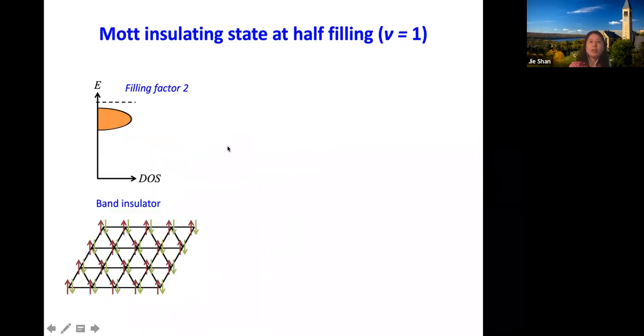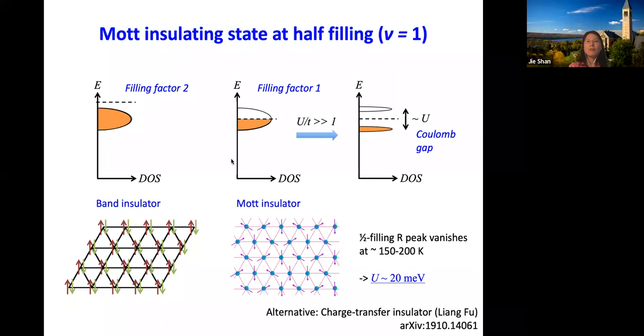Filling factor 2 showing insulating behavior is quite understandable because, even in the single particle picture, now we have a band insulator. At half filling, the physics is pretty much as what we discussed. In the limit of a large U over T, the interaction splits this band into upper and lower Mott bands, separated by this U Coulomb gap. And that's why we see a large resistance peak. And from the temperature dependence, we can also estimate how large this U is. It's a little bit underestimated. So in this case, it's 20 meV.